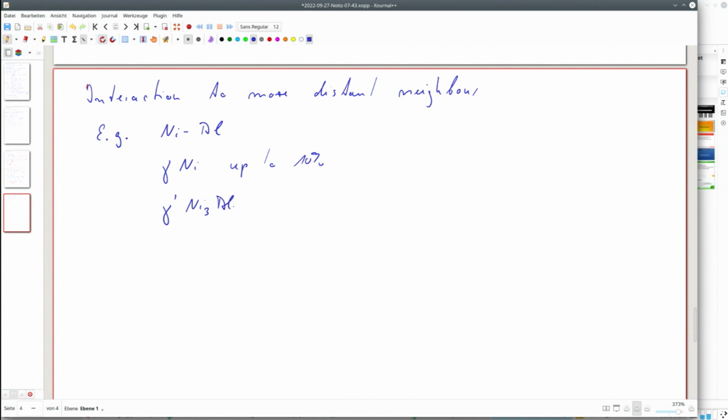And that's the basis of these superalloys, this gamma prime, at roughly 25%. This nickel-3 aluminum phase has this L12 structure, which I already mentioned. So if you like, it's the ordered FCC.